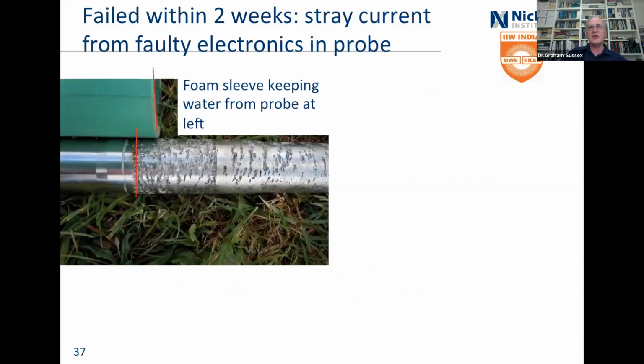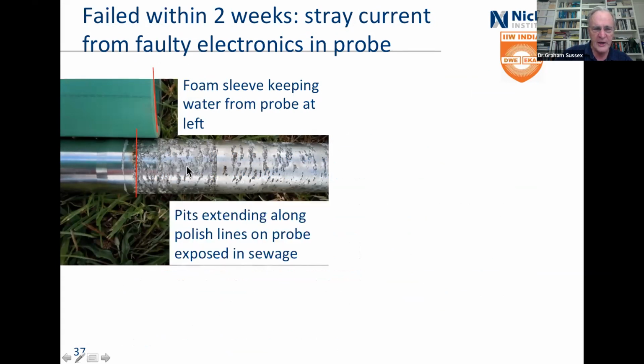Okay, let's look just at the bit where stray currents are a problem. Here we've got a sensor, which was actually immersed in a sewer pit because they wanted to measure whether they were going to have an issue and what their dosing had to be. When I pulled it out, this sleeve was up back here. Here the thing's been polished round and round, and the pits on it are extended along the polish lines. That's not so surprising. Down here, that's the crevice where this actually sealed, because that's a tapered fit there, and that's just the flare.